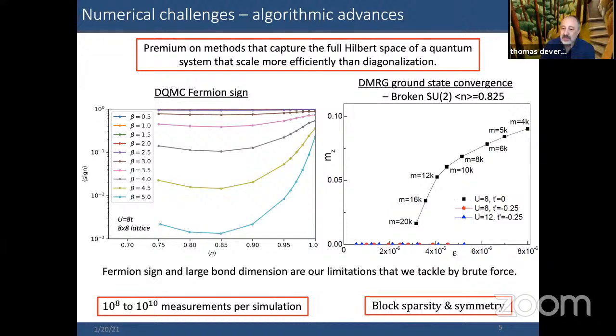But here is an example of keeping a large enough number of states when one does the DMRG convergence, to make sure that you are getting properties of the ground state that you know they should have, in this case, SU2 symmetry. In some cases, it works very, very well. And in other cases, the number of states that you need for a given level of convergence has to get increasingly large. And this gets worse as you increase the dimensions, the number of leg ladders, for example, that you want to try and simulate. So one advantage is to write the code so that it respects some of the symmetries that should be employed, like SU2, and take advantage of simple block sparsity to make the calculation able to handle more states than you might normally have a decade or so ago.